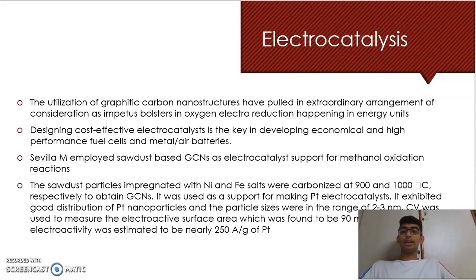The sawdust particles impregnated with Ni and Fe salt were carbonized at 900 and 1000 degrees centigrade respectively to obtain GCNs. It was used as support for making platinum electrocatalysts. It exhibited good distribution of platinum nanoparticles and the particle sizes were in the range of 2 to 3 nanometers. CV was used to measure the electroactive surface area, which was found to be 90 meter square per gram of platinum, and the electroactivity was estimated to be about 250 ampere per gram of platinum.